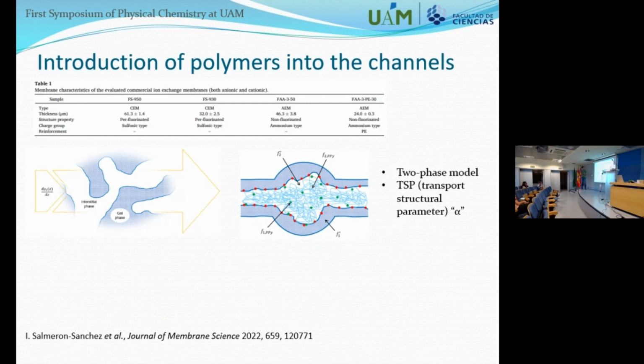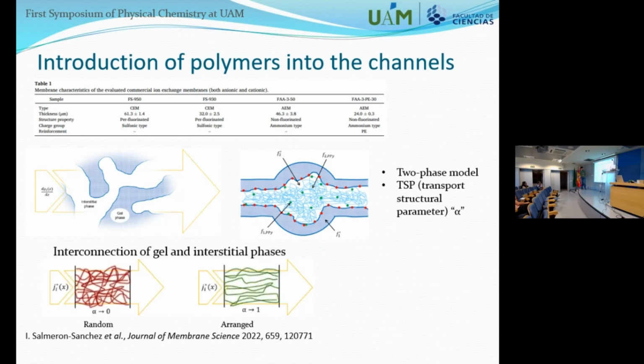And in this model, we have this TSP, transport structural parameter, that helps to relate how is the conduction of the ions through the membrane. So it says how is the interconnection of the gel and the interstitial phases that we have within the membrane. When it's close to 0, it's related with a random interconnection. And when it's close to 1, it's connected with an arranged connection that helps to promote the conductivity of the ions.